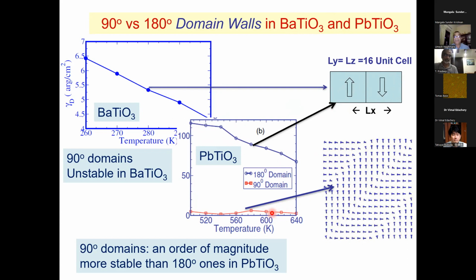I'm not bringing in experimental details here, but this demonstrates that using combination of first principles calculations and modeling, we are able to predict not only phase transitions, structural phase transitions, but also inhomogeneous ordering and domain wall structure of these interesting functional oxides.